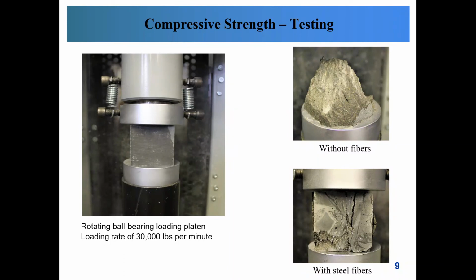Rotating ball-bearing loading platens were used for testing the cubes in compression at a loading rate of 30,000 pounds per minute. Tests typically run from 2.5 to 4 minutes. Without fiber reinforcement, the cubes failed explosively. The addition of sufficient steel fibers changed the failure from being brittle to ductile, as you can see in the pictures to the right.